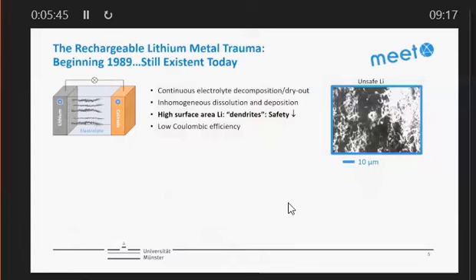What is the problem of lithium metal batteries? And this is very well known. Since 1989, it became very public because batteries which were on the market caught fire, is the so-called dendrite formation. I like to call it high surface area lithium because dendrite is just one of the many morphologies that can happen when you deposit a metal on a substrate, including lithium. And the safety goes down and performance also goes down.